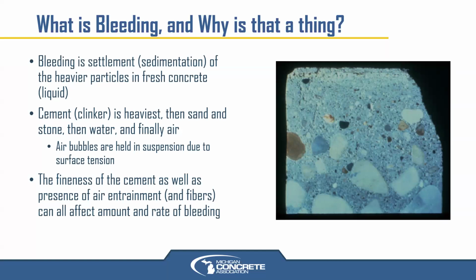But the fineness of the cement, and type 1L being slightly finer probably than its type 1 counterpart, as well as the presence of air entrainment can affect bleed, and fibers in the mix can affect bleed. The specific mix design can affect bleed. The aggregate type or shape can affect the bleed rate.